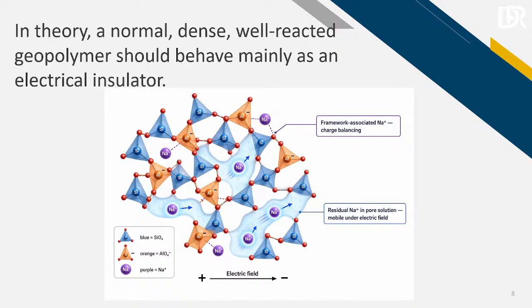That's why we design for Na over aluminium to 1, so we can have a stable material. But the issue is that no matter how hard we try, we can't get close to the theory, and you will have excess liquid or activators lying around, and when they are drying and they get in touch with the humidity in the atmosphere, they will show conductivity.